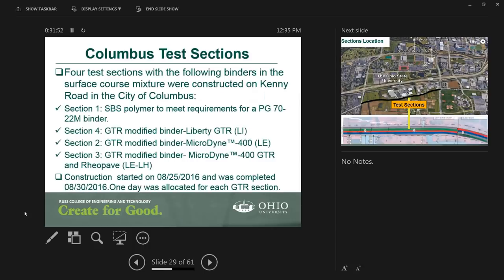We had four test sections that you can see here. One was a control section where we used a mixture with a polymer modified asphalt binder meeting PG 70-22. In the others, we used GTR mixtures with the GTR binder with the Liberty. We also had a GTR binder with a Microdyne 400, which is the Lehigh, and another one where we used the Lehigh GTR as well as Rheopave. Construction was done in August of 2016.